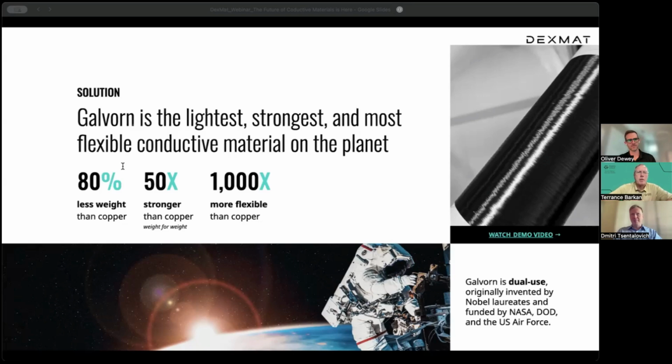So there is a limit, because the way that the fibers that we make work right now in terms of strength is you are not breaking the nanotubes. If you take a fiber made of carbon nanotubes that are highly aligned and you do a tensile strength measurement and pull that fiber apart until it breaks, it's not the nanotubes that are breaking, it's the nanotubes slipping past each other. And it's these frictional forces that give the fibers the high strength.